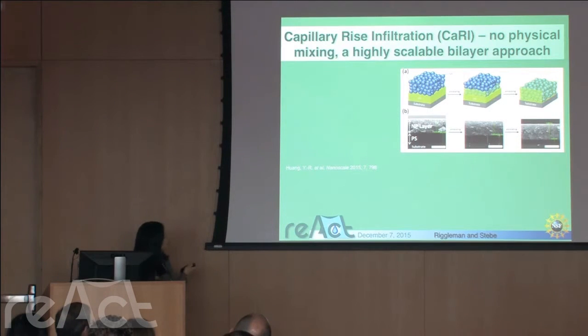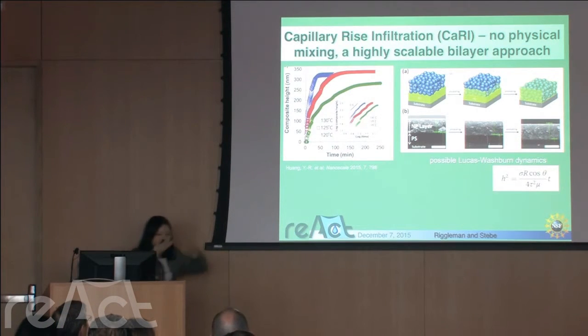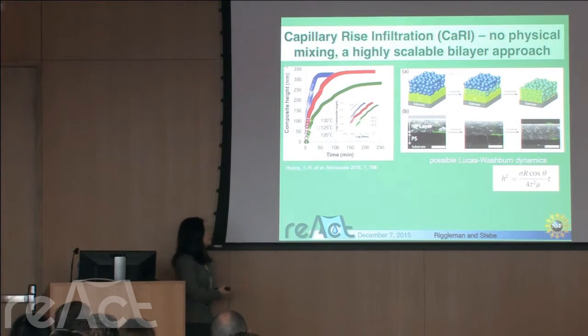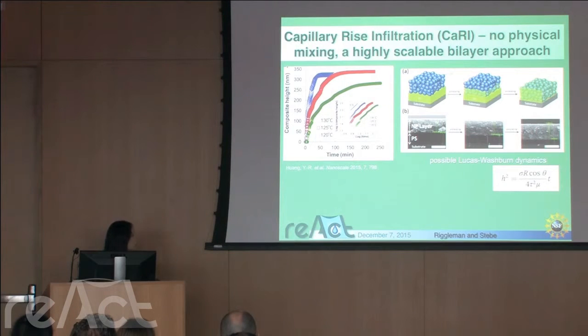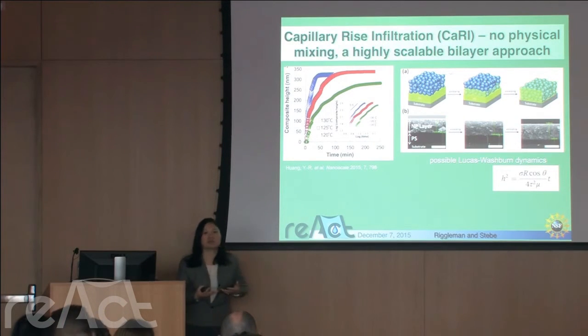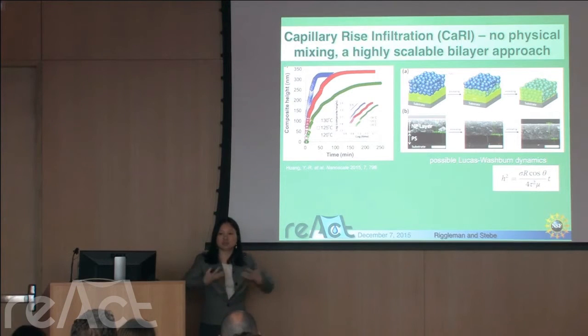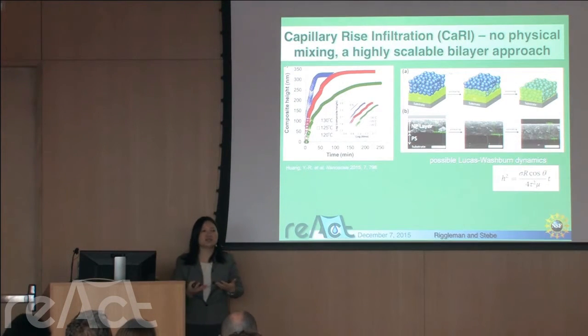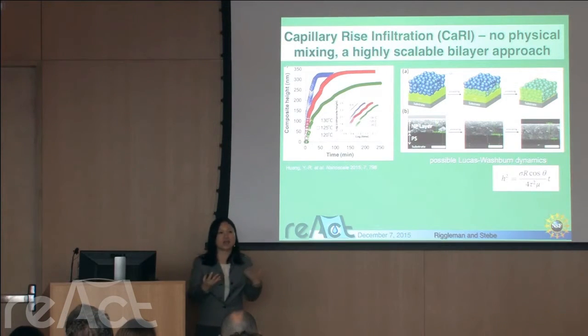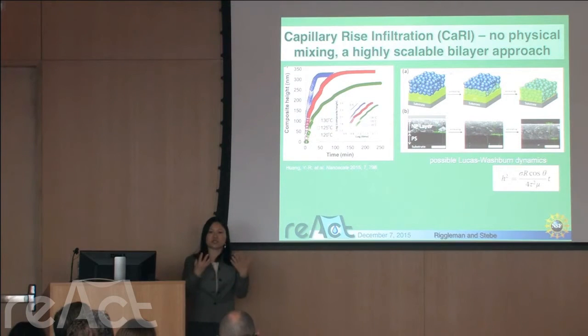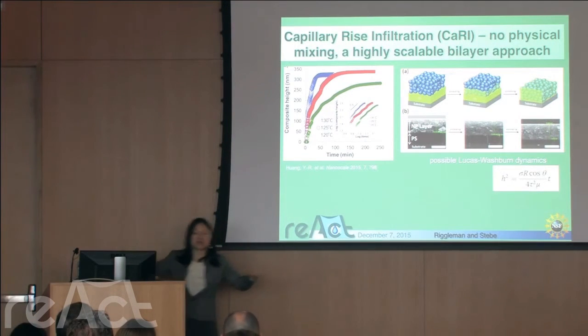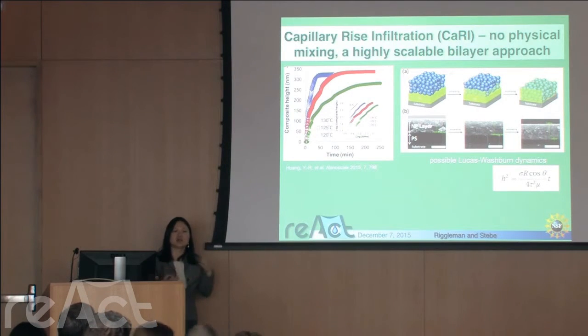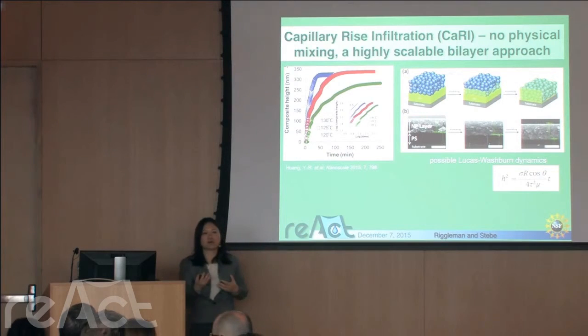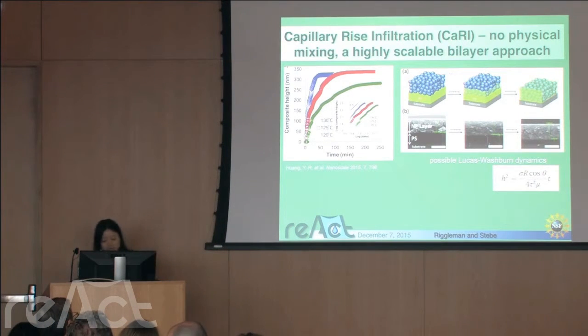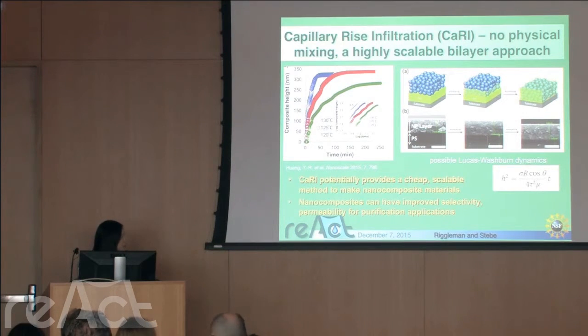So here is one example, showing the polymer infiltrating from the bottom into the nanoparticles, more or less fitting the Lucas-Washburn dynamics, right? So the question is, if we want to make a membrane, it should be porous and should not be completely infiltrated into those interstitial spaces. How do the particles interact with polymers, and how are wetting and de-wetting encouraged? Although they infiltrate, the polymer should glue and connect the nanoparticles. On the other hand, you still want to maintain high porosity. So what is the preferable wettability between the polymer and nanoparticles? What is the polymer size? What is the chain size? And what are the dynamics of this kind of migration, and so on, right?